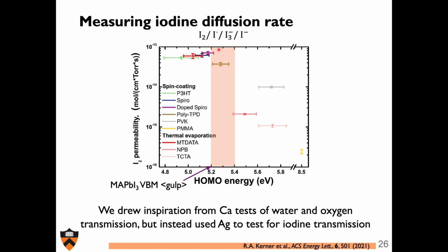This energy around here is what we associate with the iodine, triiodide, iodide redox couple. It's going to be somewhere in here, and that's where we see a massive transition from fast redox-mediated iodine transport to much slower redox-mediated iodine transport. And unfortunately, the HOMO energy of methylammonium lead iodide, or any iodide perovskite, sits right here. So if I want a hole transport layer that's capable of injecting or extracting holes from the perovskite, it's also unfortunately capable of being doped by iodine and being this sort of readily mobile circuit for iodine transport.